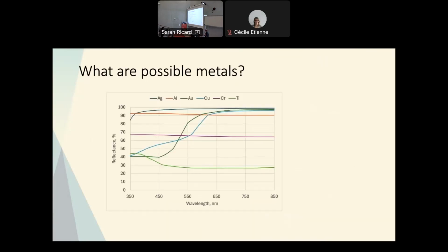If you take these different optical properties and take into account dispersion, which is something I haven't done yet but am doing now here, you can see the reflectance as a function of wavelength for these various metals. Silver is the best metal for the visible and infrared. Then, if you talk about a broadband reflector, this is aluminum, which is what we find. And then copper and gold for longer wavelengths, and titanium or chromium tend to have low reflectance.